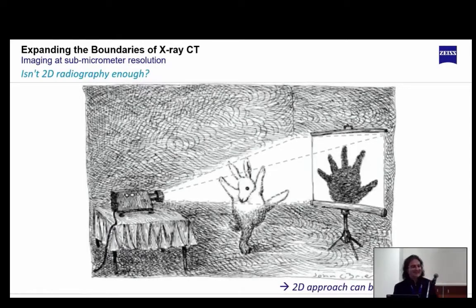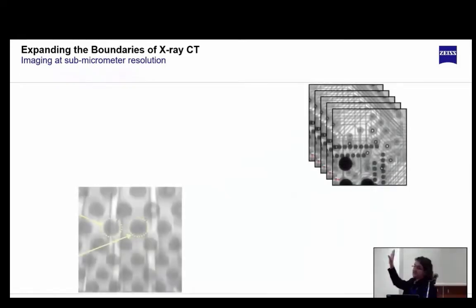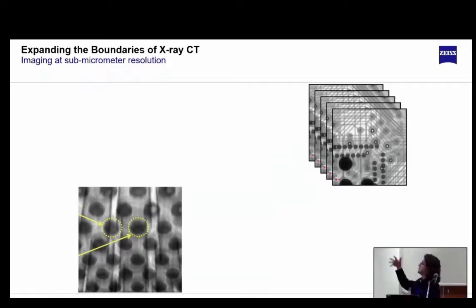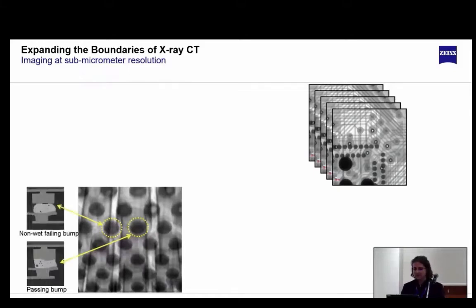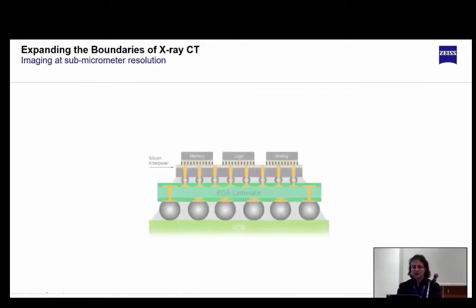So the 2D projection can be misleading, and we can see it from this example. It's because you have radiographic projections in which you have the back layers and the front layers, and you might see a low density that might look like a void, but you are not quite sure. And even if you think it's a void, you don't know exactly where it is in space. So by using 3D X-ray computed tomography, you can actually slice virtually in the 3D volume and see if those are actually voids or not, or any other kind of defect. So that's the main advantage of having 3D information.